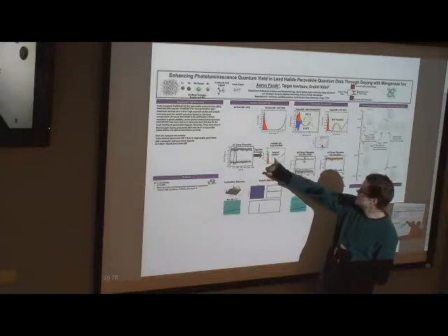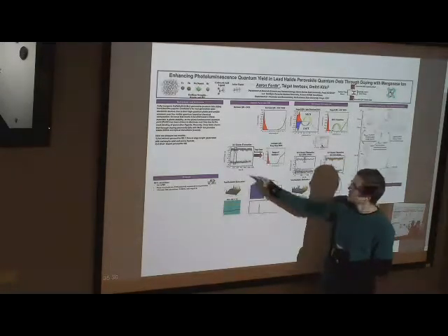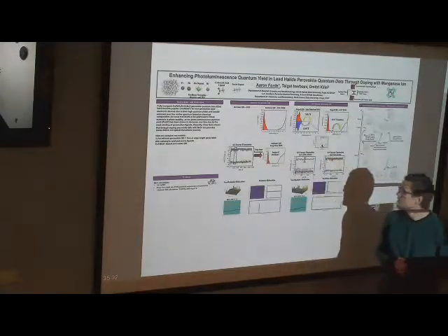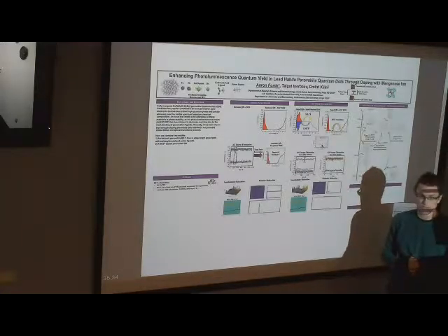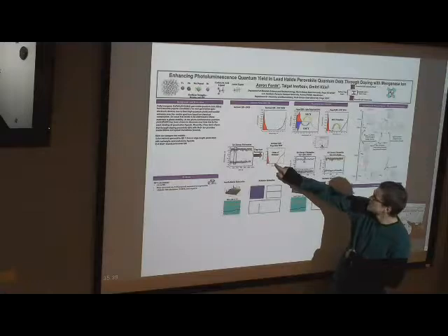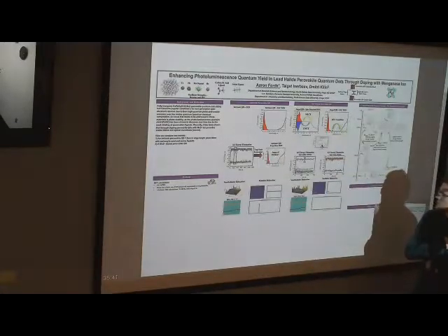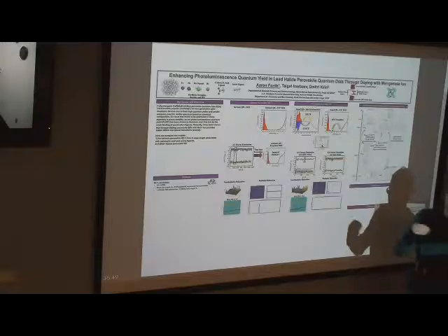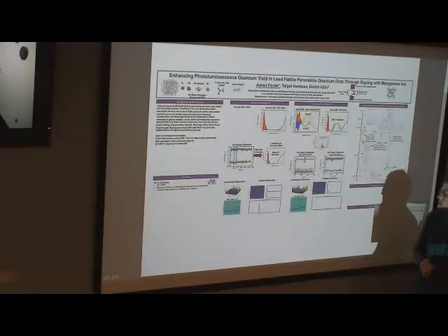And then that's what this density of states plot is showing here. I just picked one of the positions along the trajectory, did a single point calculation, and there's a faint little trap state near the valence band edge. And so that kind of shows that over time you can get ligands coming off, going back on. If you run it long enough, you expect some ligands to eventually fly away from the quantum dot.